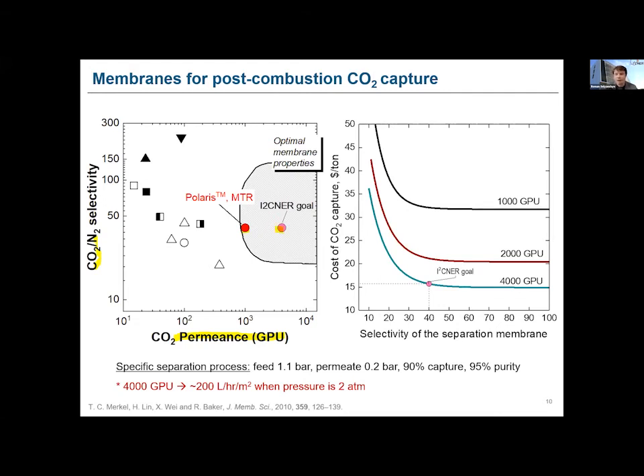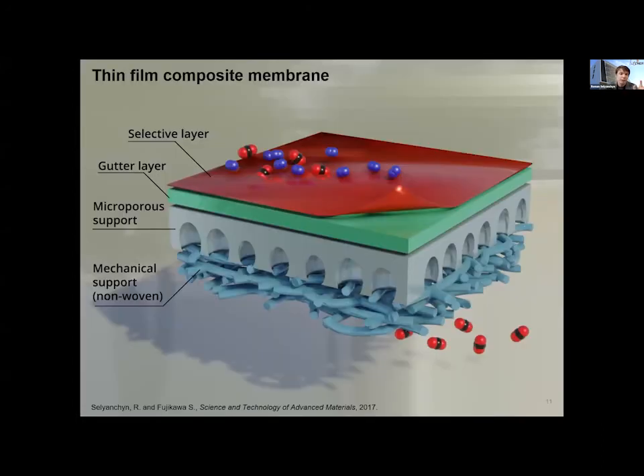And this pink point at that time was our institute goal, which was set almost 7 years ago. And the main problem at that time was how to achieve these high permeances which are required for optimal membrane properties, right? You see this gray area is optimal membrane properties, and there is not much literature data. And we wanted to achieve membranes in this area in order to satisfy the requirement for low-cost CO2 capture. And if we would develop this membrane, it would provide us about $15 per ton of CO2 captured.